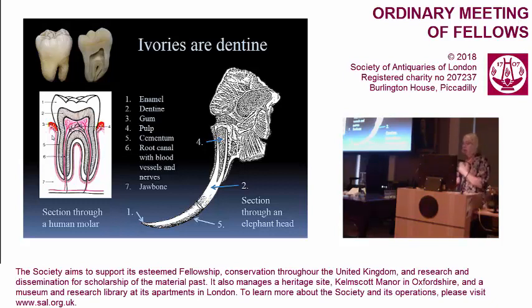In open-rooted teeth like elephant tusks, you have a conical pulp cavity, and as more layers of dentine are laid down around it, the pulp cavity remains open — it's just like stacking ice cream cones into each other. So gradually the tusk grows down and forwards, away from the skull, and more ice cream cones are pushed in at the back. The newest, most recent dentine is right up around the pulp cavity. In cross-section, the material is made up of cone-within-cone shapes of fine layers of dentine around a conical pulp cavity.